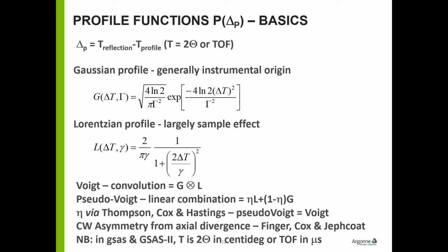There are slits, which are squares, or rectangles if you like. There is the shape that comes off the monochromator, the shape in the source. And there's something called the central limit theorem, which says that if you take a whole lot of these different functions, all symmetric, convolute them together, the result will be a Gaussian, if you throw enough of them together.